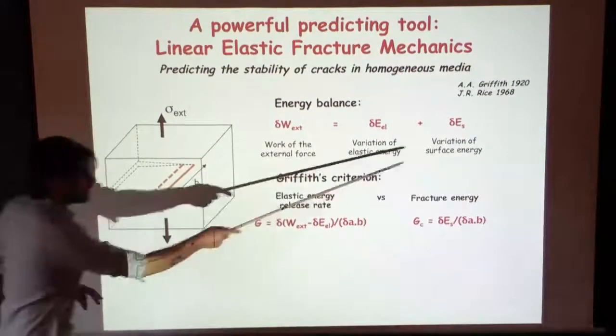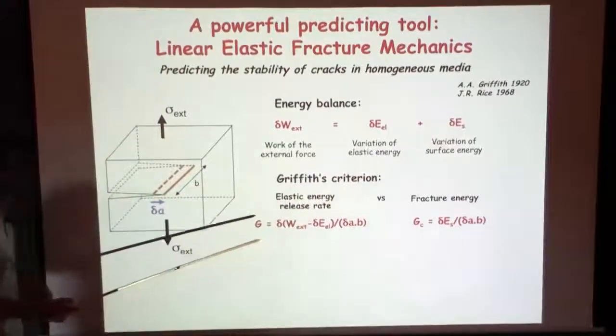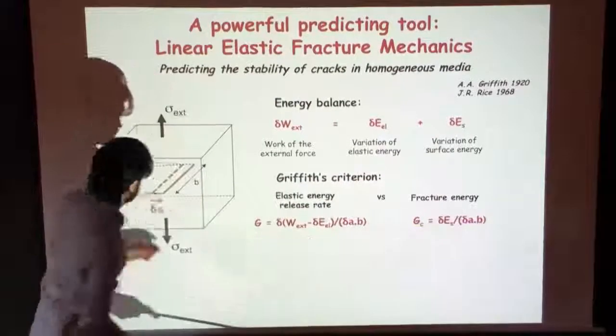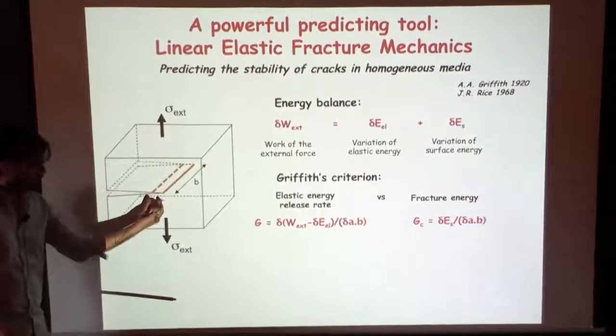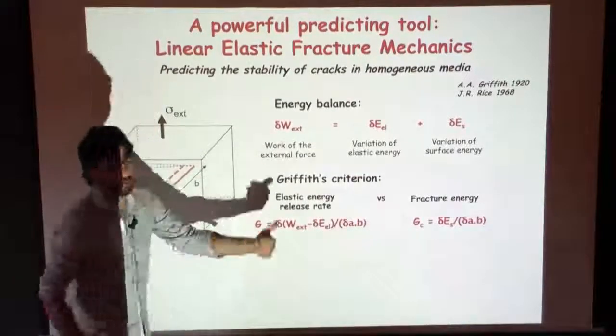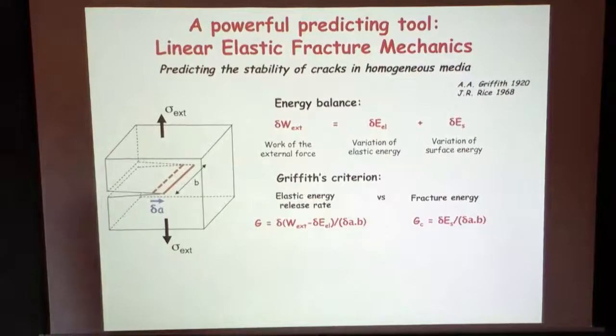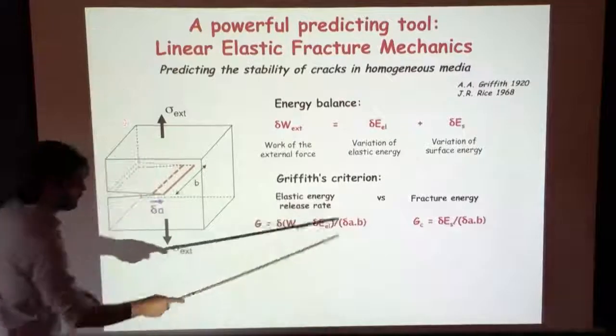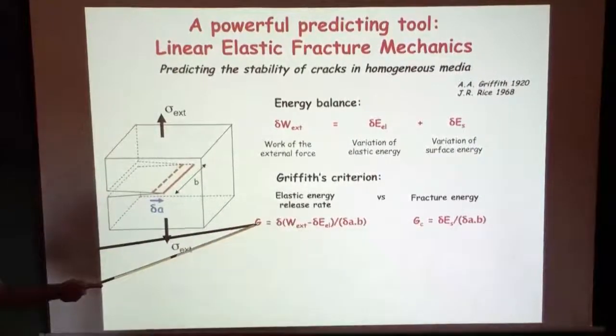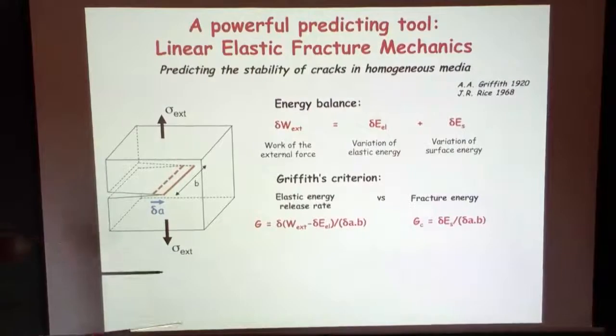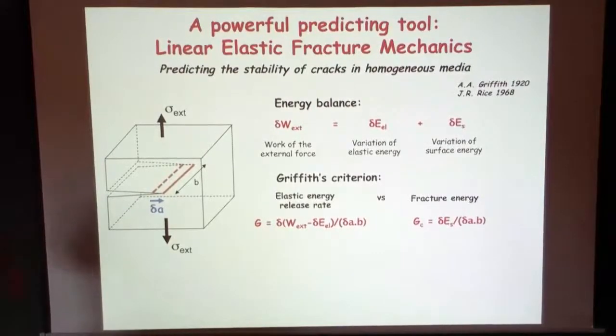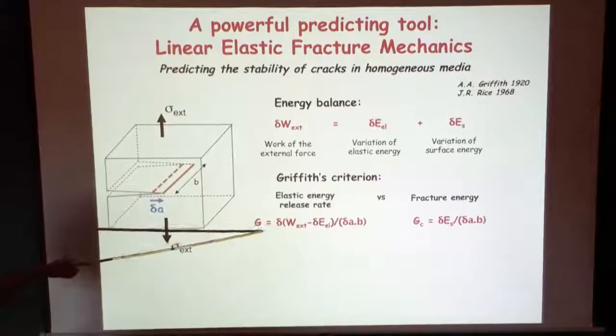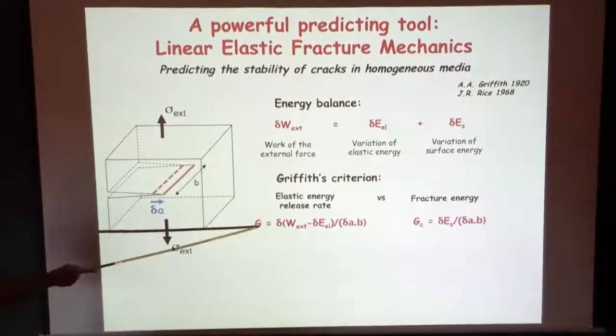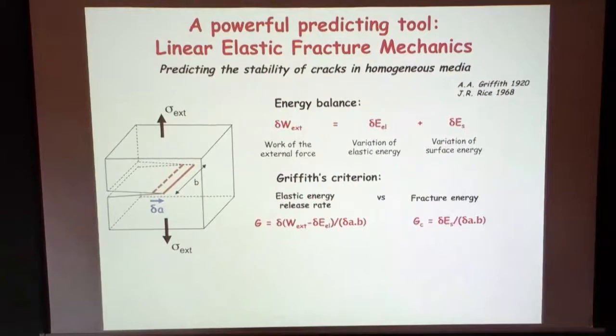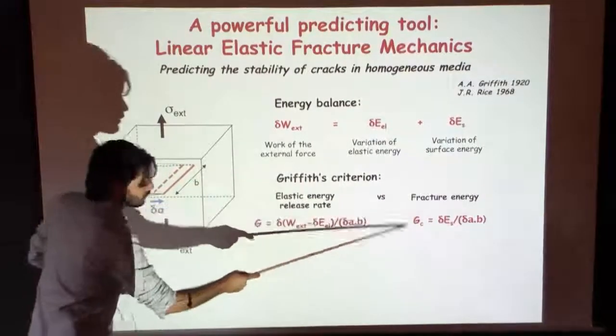Same thing for the dissipation. Instead of looking at delta E_S, I'm going to normalize it by the surface over which the crack moved, and I'm going to have a rate of energy dissipated to make the crack propagate over some unit surface. So I have my relevant quantities: fracture energy and elastic energy release rate. That will be the one we use all the way through the remainder of the talk. You already feel that this is a thermodynamical driving force, the energy you gain as the crack moves on, and this is a resistance to crack growth, the fracture energy.